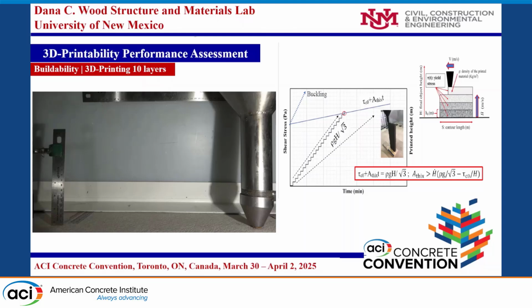And the increase of the static yield stress needs to be higher than the given ratio, which is the weight times height divided by the square root of 3.